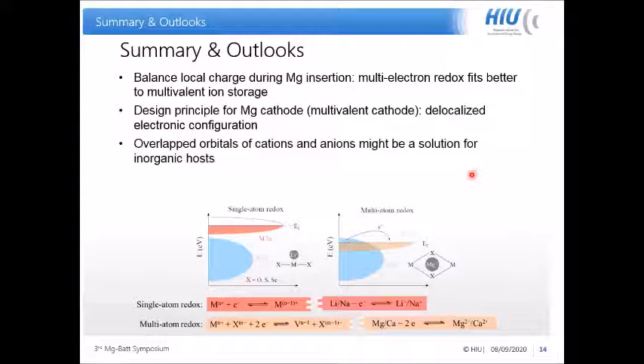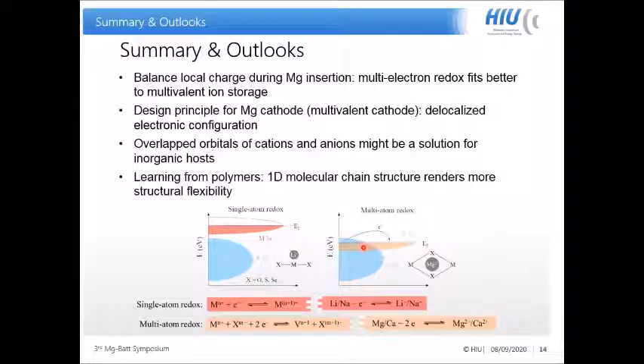And we know that a delocalized electronic structure could be easily achieved in organic cases, where it's easy to have a conjugated structure. But in the case of inorganic materials, we have to engineer the band structure of the material so that we have some overlap of the orbitals between the cations and anions, and this might be a solution for a more dense structure compared to the organic cases. At last, we also learned from the polymer that the 1D molecular chain structure might render more structural flexibility, so that the battery system and the ion mobility will benefit from this structure. This could also be something we need to consider when we further design a magnesium cathode.